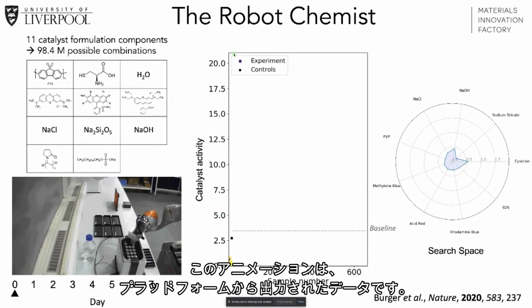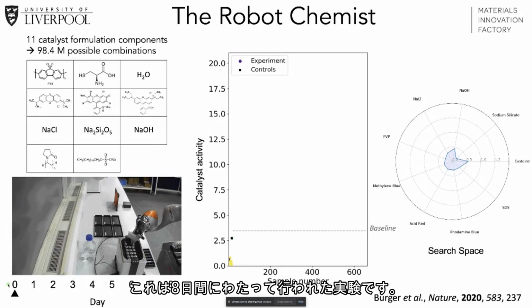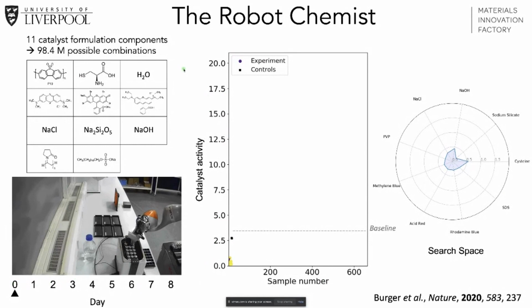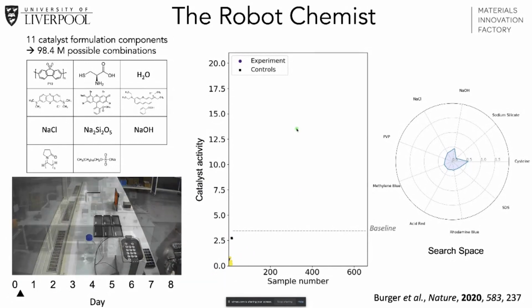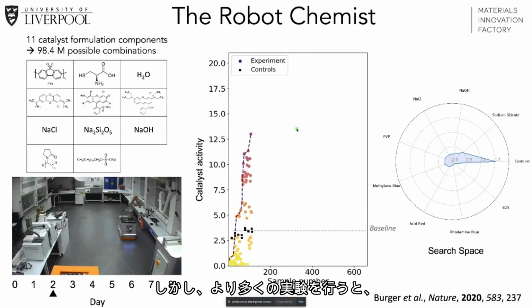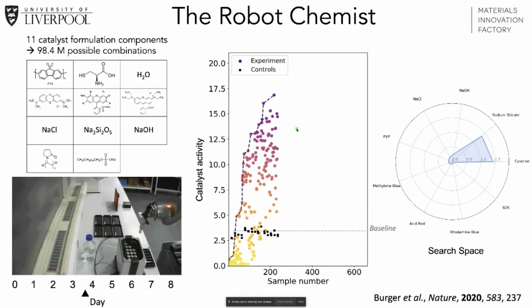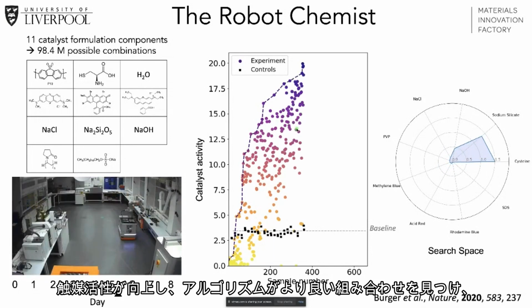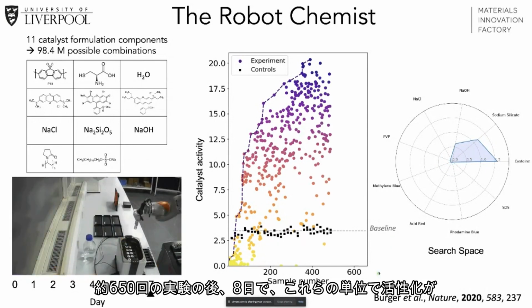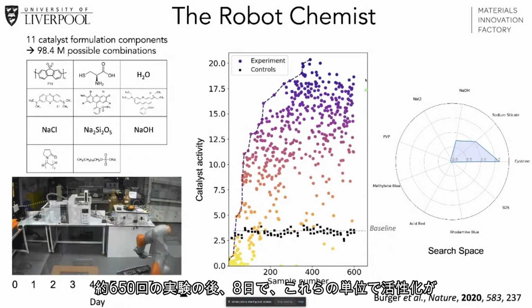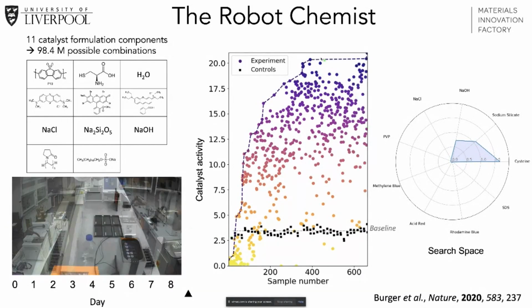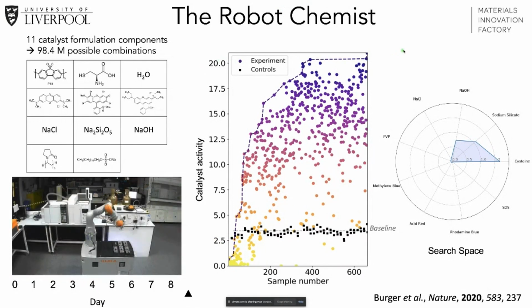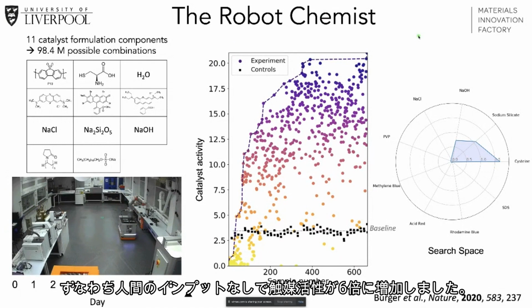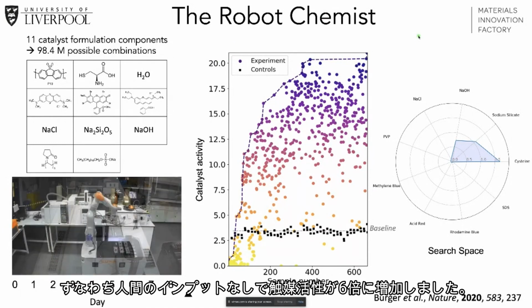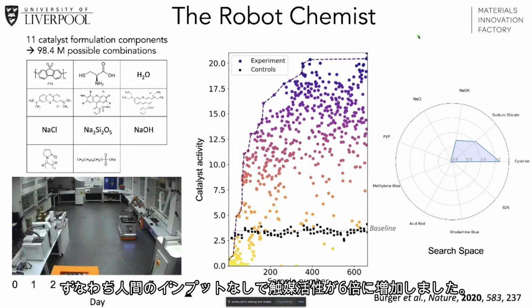So this animation shows the data as it comes off the platform. This is an experiment that ran over 8 days. And you can see the catalyst activity starts quite low because the initial conditions are random. But then very quickly, as you do more experiments, the catalyst activity gets better. The algorithm finds better combinations. And after about 650 experiments or so and 8 days, we've gone from an activity of about 3 in these units to an activity of more than 20. So we've got something like a six-fold increase in the catalyst activity without any input from a human. So it's completely autonomous optimization.